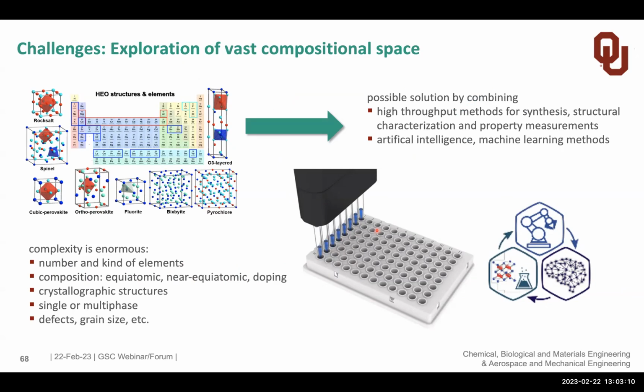If you look at the opportunities we have in playing around in a material system which can use a lot of the elements in our periodic table, it can result in all the different structures which I have presented, a few of them to you. We can play with a composition between equiatomic, so 5 elements at 20% each. But we can also put 15 of one and 25 of the other. So we have a huge, gigantic compositional space which we should explore in order to get the best composition.